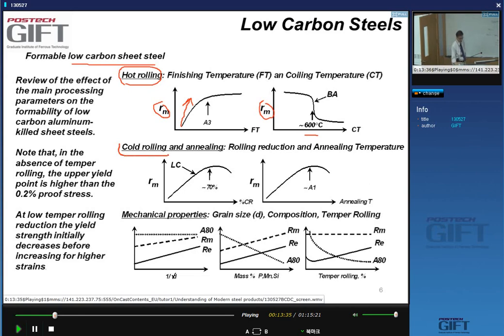In the cold rolling, so the same material, and in the annealing, we'll also see a dependence of the R mean value on the processing. For instance, the more we cold roll in general low carbon steel, the more we pancake the grains, and get the grains oriented in such a way that we get 111 parallel to the normal direction after annealing. We cannot, however, over deform the material. If you do more than 70% of deformation, the R value decreases again.